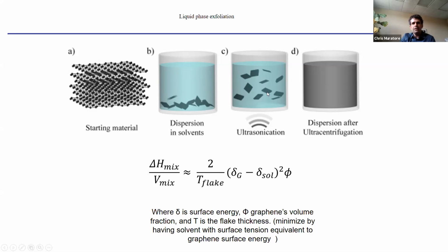If you want this suspension to be stable, if you don't want these particles to segregate out because of density differences, transition metal dichalcogenides are usually made of pretty heavy elements, then you want to pick a solvent that has around the same surface tension as the surface energy of the material that you're exfoliating.